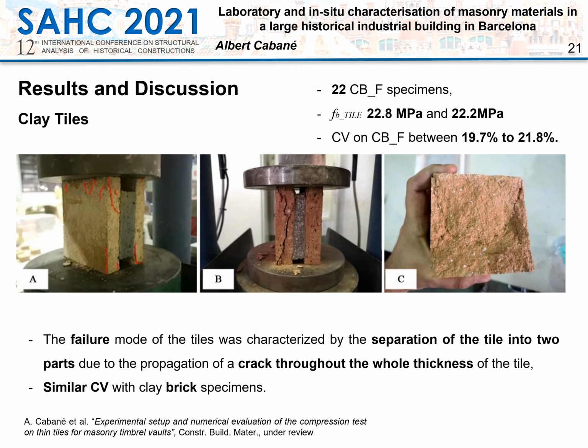Finally, the results obtained for the 22 assembled tile specimens were satisfactory. These results have been characterized by satisfactory coefficients of variation for historic handmade fired clay units. These were 20% and 22%, similar to the brick specimens tested in this campaign. The failure mode of the tiles was characterized by the debonding of the tile into two parts due to the propagation of a crack throughout the whole thickness of the tile. This means that stresses were developed inside the tile.